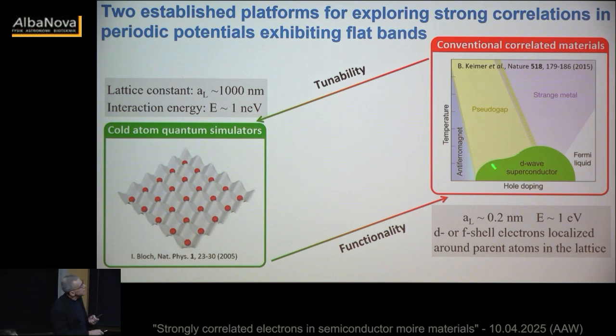Okay, now the difficulty here is that while I can tune the atomic density and this lattice as I will, here I have very little tunability. Every line here would require a different sample. Right? The holes, the doping has to be introduced during the growth process. So in order to study this phase diagram, you have to grow a large number of materials and try them out as a function of temperature, measure their conductivity, etc. All right, so that's kind of the challenge.